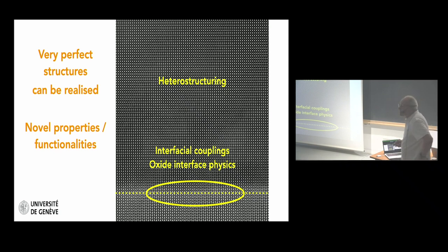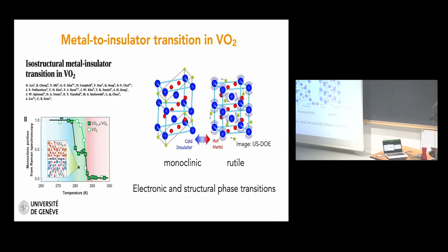So we heard yesterday already about, on Tuesday we had a very nice talk on metal insulator transition in vanadates, V2O3. Here this is an example of metal insulator transition in VO2. So the system is transitioning close to room temperature to the insulating state, and along with the transition, you have a structural transition from a rutile phase to a monoclinic phase.